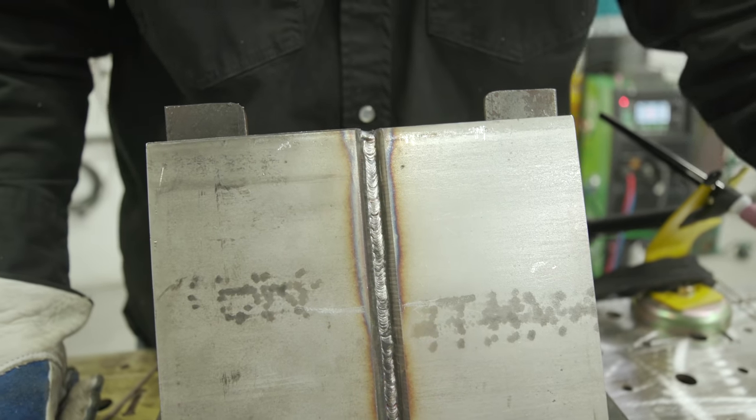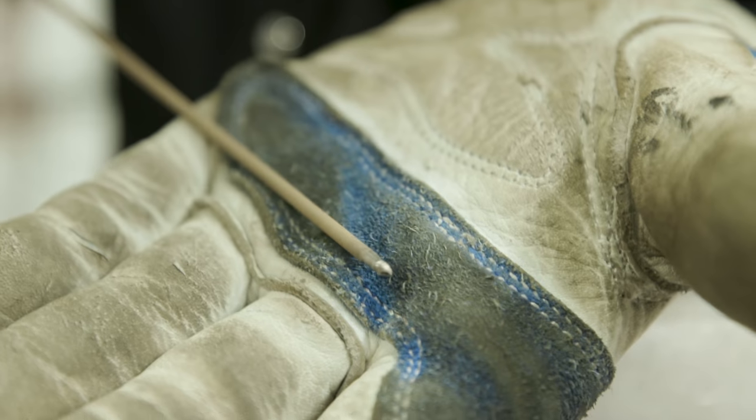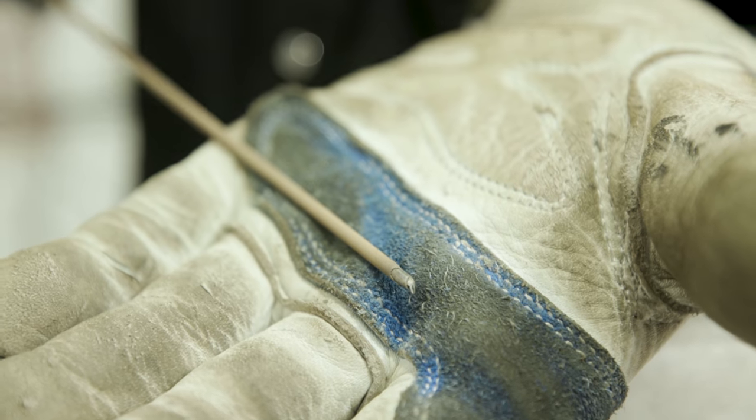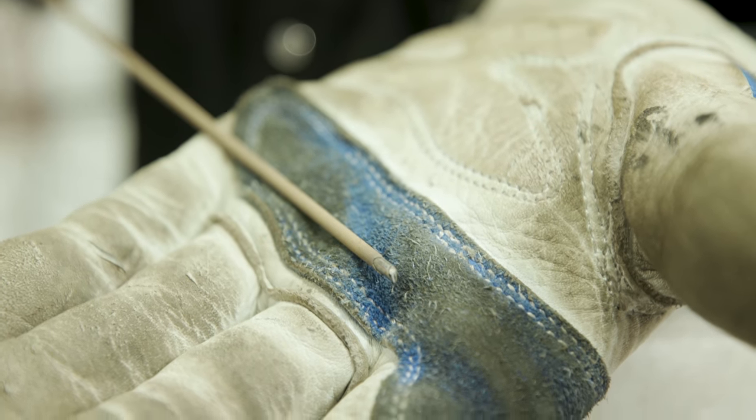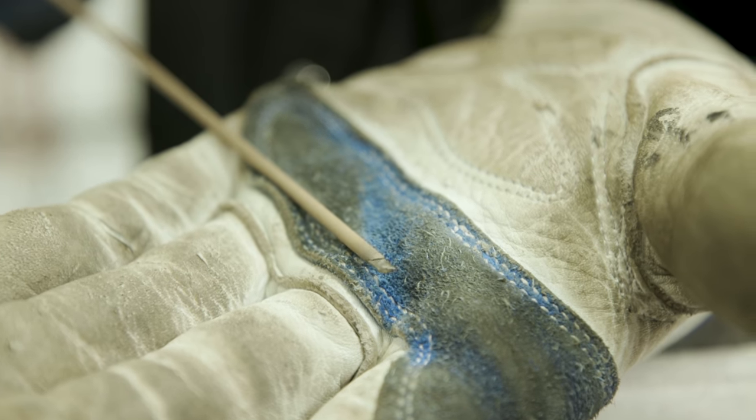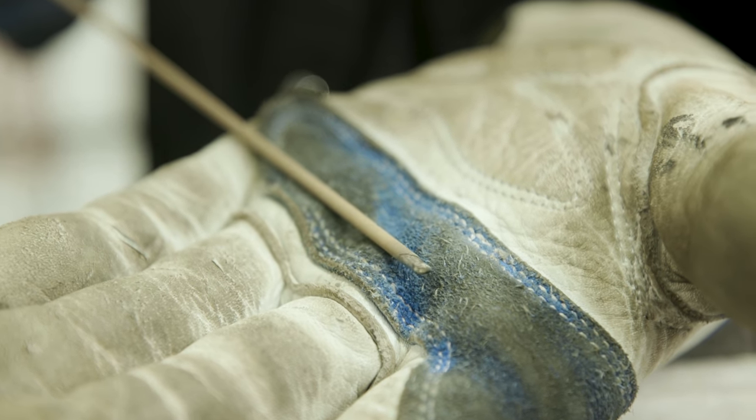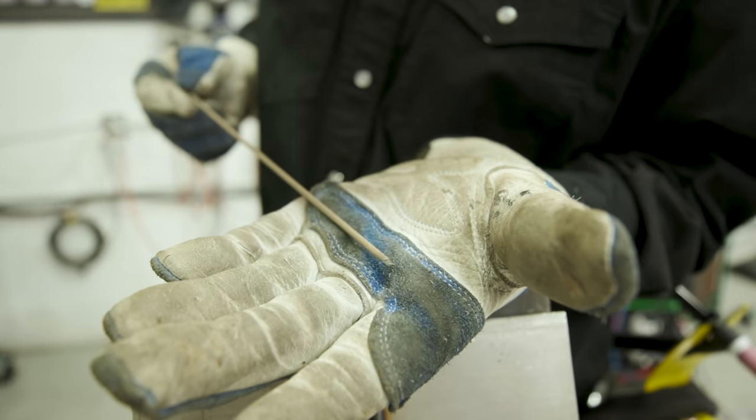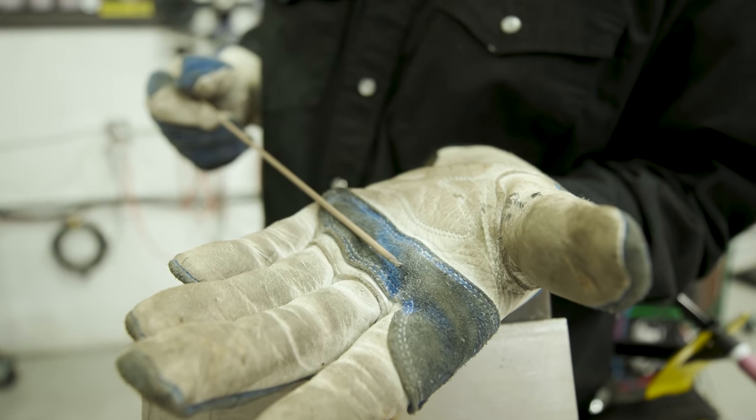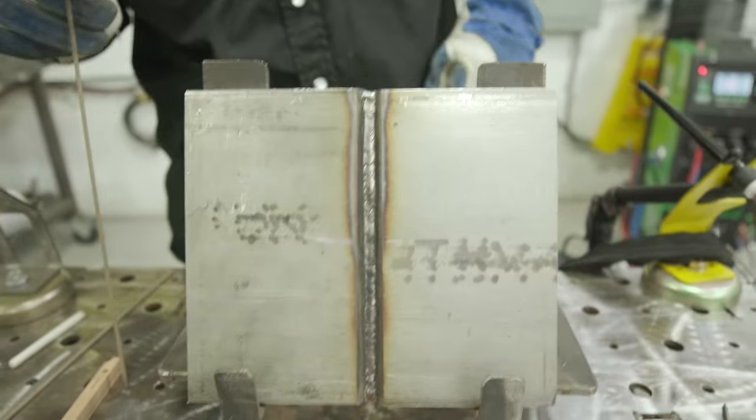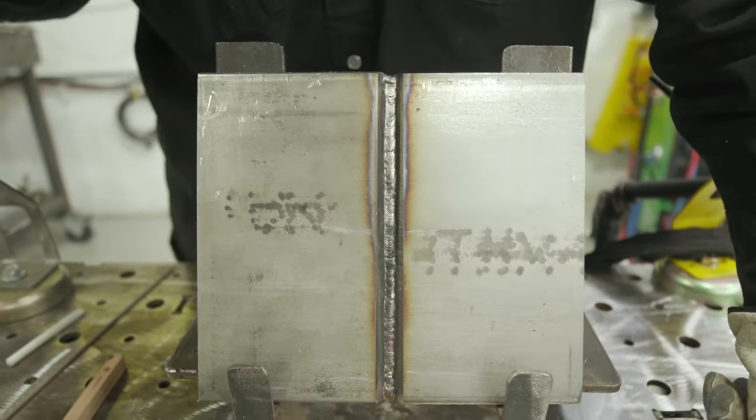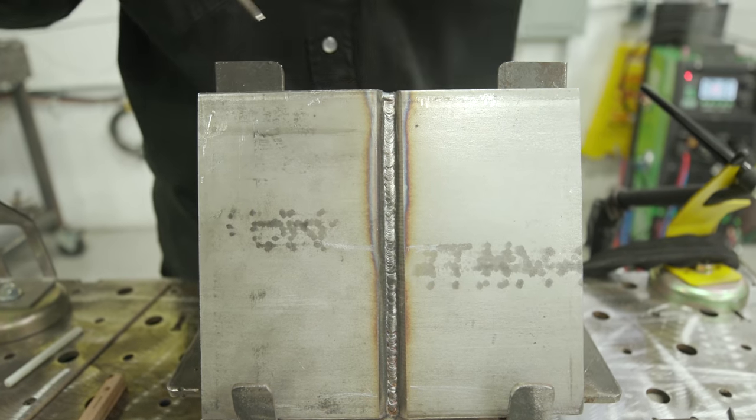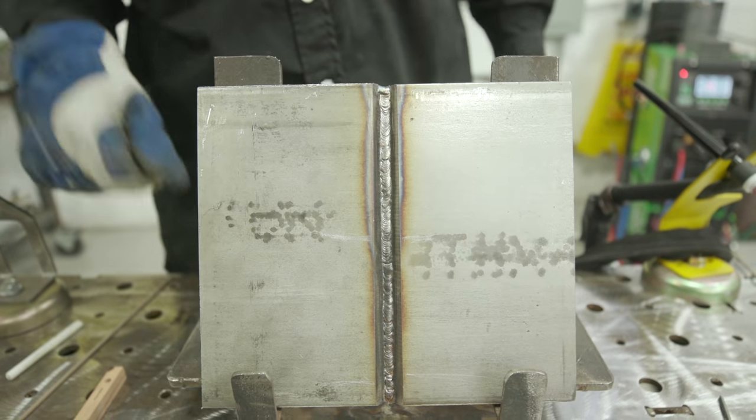All this is the flux protecting the coating right here. We'll see if we can wire brush this off - it's not chipping off so I need to get a wire wheel. See how it just came right off? There's no sugar or nothing, the flux is protecting the weld from the atmosphere, creating its own envelope. If you notice right here, it's not burned like you would see a normal 3/16 or 308 stainless filler wire - it's silver still. That's kind of cool.